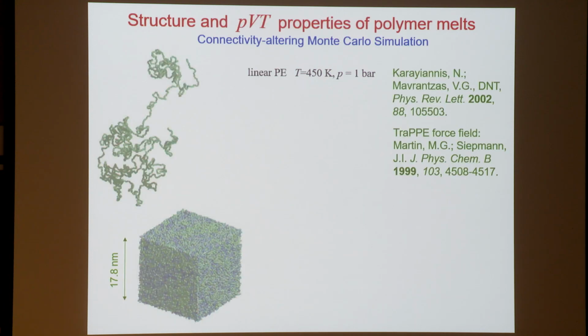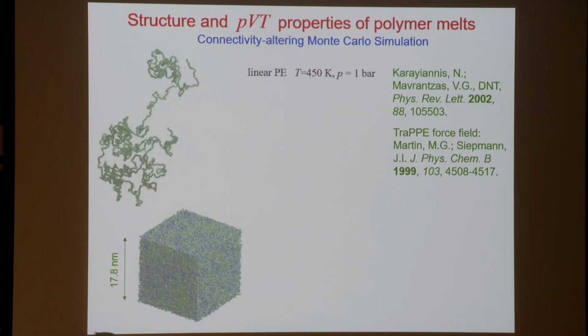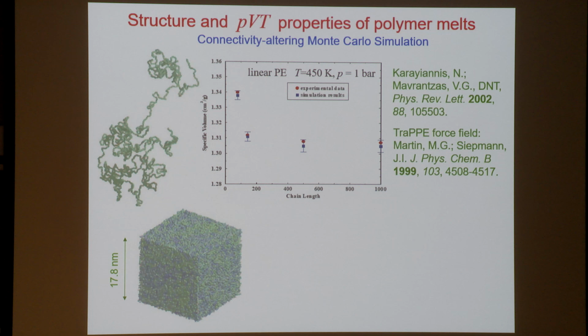And as an example of a result that one can obtain from this, I show you results from simulations of polyethylene melts. We have a box with periodic boundary conditions filled with segments of polymer chains. A chain may look like this. This is a C6000 chain. We use a force field for the representation that has been validated for small molecular weight alkanes. We completely equilibrate the polymer at all length scales under 450 K and 1 bar, and we can calculate, for example,